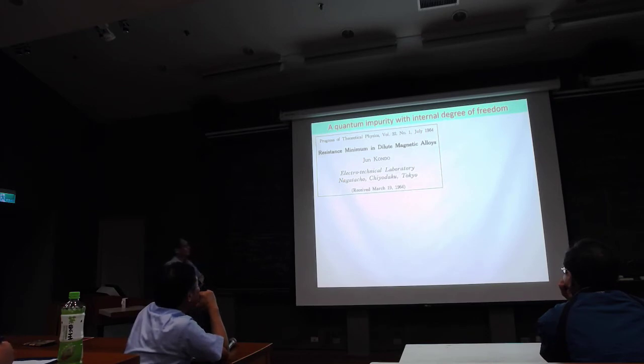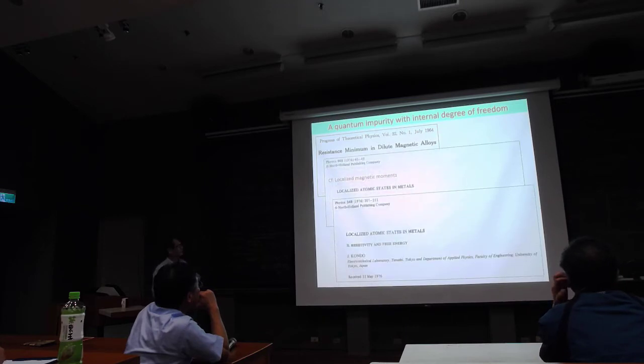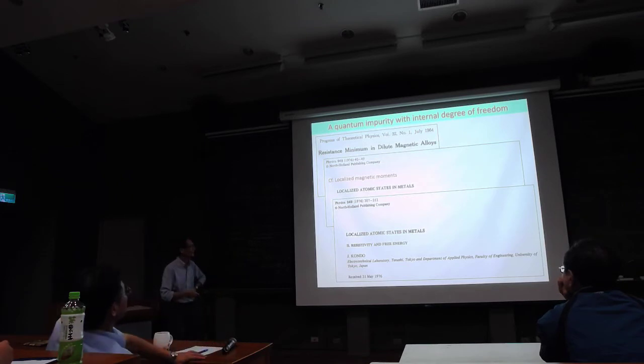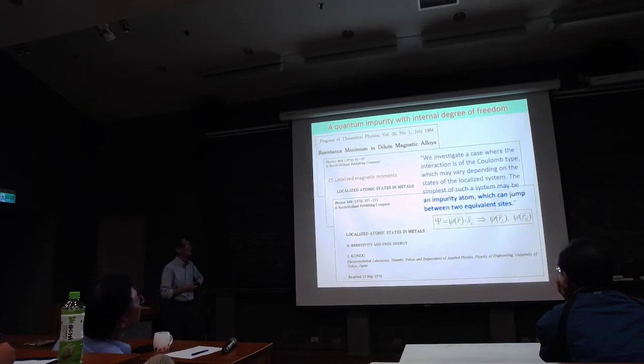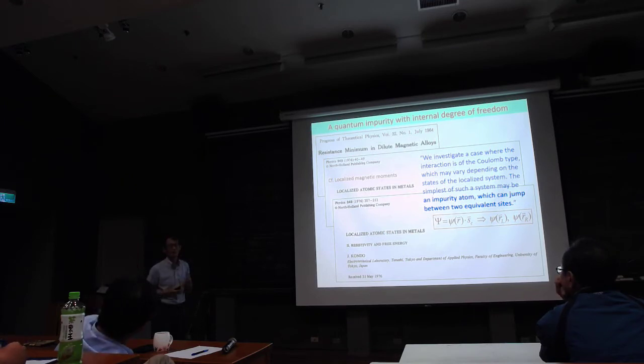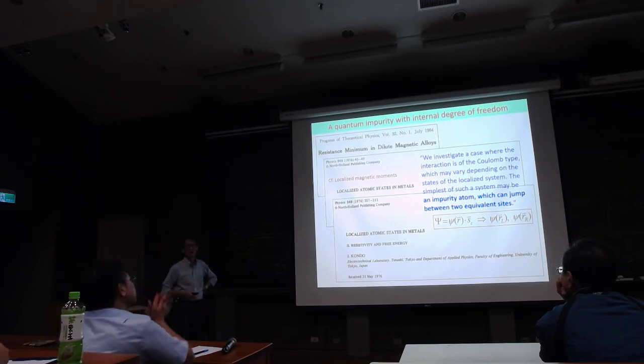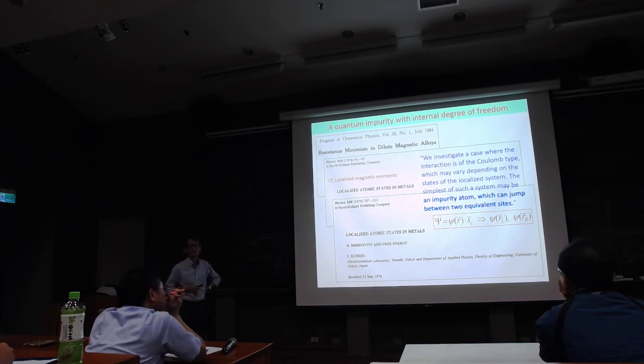1964, this work. But it is very interesting that in 1976, Kondo published another two papers together. He actually realized that you don't need a spin half. All you need is to have an impurity. That impurity can switch back and forth, in a double well potential or two equivalent sites. If this defect can switch between these two sites, then when it interacts with conduction electrons, you can also obtain this Kondo physics.